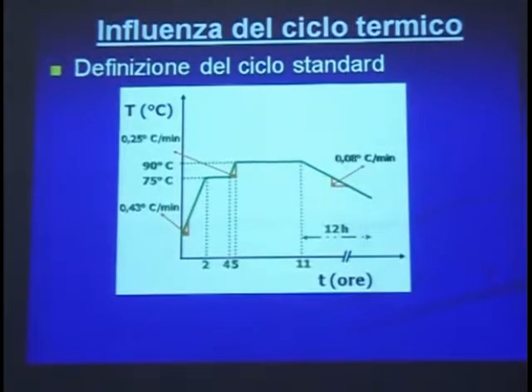This is the standard cycle. This has been set. There is a heating rate up to 75 degrees C, and then a second step at 90 degrees C, and then the cooling down. The first part of the cycle before the cooling is 11 hours, and then the cooling takes place in 12 hours. So it's a total time of about 24 hours.